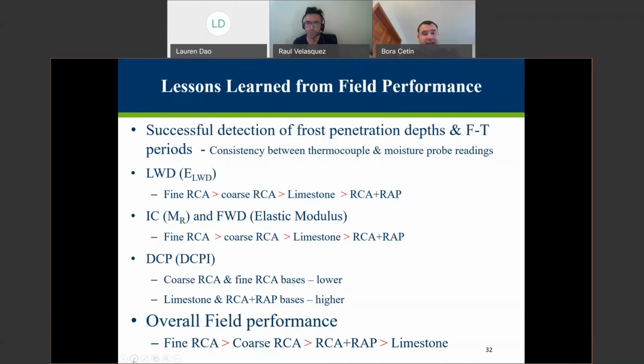DCP shear strength values were a little bit lower for RCA bases, but it is really a very tiny point that we take with the DCP. So the data that we collect from the LWD, intelligent compaction, and FWD seem to be more reliable when we look at the overall field performance. On the other hand, in the 2.5 years of data that we collected, fine RCA and coarse RCA really outperform, providing better stiffness and performance compared to limestone aggregates, and RCA+RAP provided a little bit lower performance than the fine and coarse RCA, but had higher performance than limestone throughout that 2.5 years of monitoring.